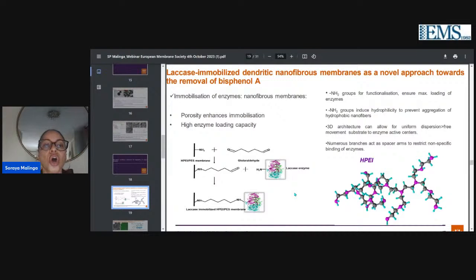So why we went the nanofiber route is that nanofibers are known for porosity enhancement. They are known for high enzyme loading capacity. The HPEI, in a way, we wanted to ensure that we have maximum loading of the enzyme because of the numerous amine groups. They also assisted in the fact that they would induce hydrophilicity. Also, literature does state that if you have a hydrophilic component with your enzymes, it does prevent aggregation.